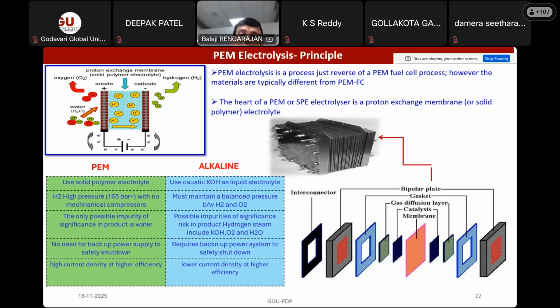Because in alkaline, you have to take pure water and add a salt, KOH (potassium hydroxide) or sodium hydroxide, to make the water conductive. Whereas in the case of PEM, you don't want to add any salt, because this polymer membrane, which is placed in the center of the cell, will do the ionic conduction between the positive and negative electrodes. This is a typical polythene-like sheet, and it will have a proton within the polymer matrix, which will take care of the ionic conduction between the two electrodes when you supply a potential, and you have to pass only pure water to the system.